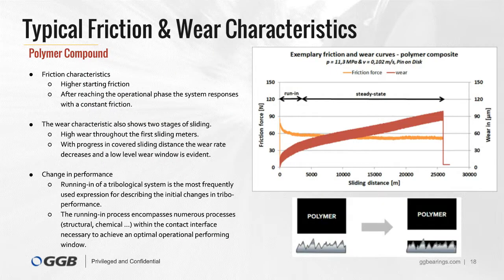On this slide we see the first outcomes, showing exemplary friction and wear curves of a polymer composite as a function of sliding distance. Friction is colored orange, and wear is red. Looking at the behavior of the material, it is obvious that it shows two typical phases in friction and wear. In most tests, the contact starts with higher friction, which declines with progress in covered sliding distance until a steady state phase is reached.